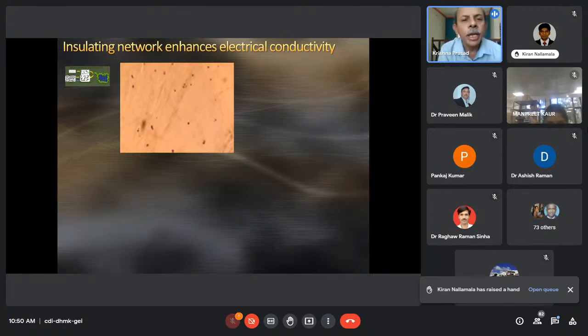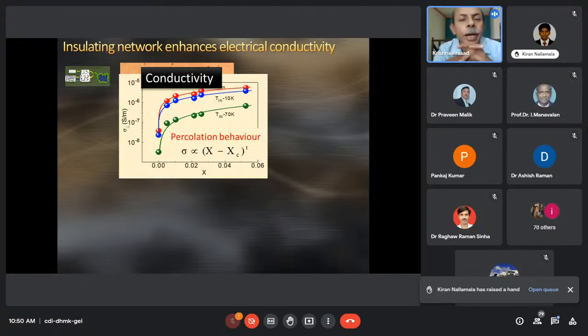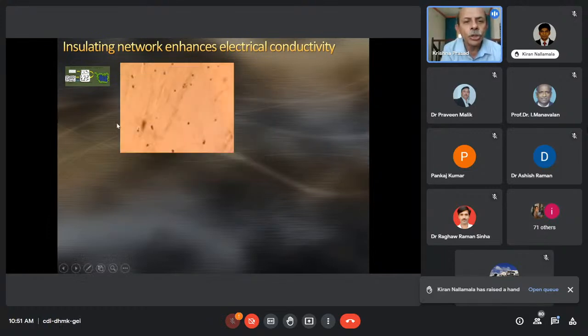And what you see here is the polarizing microscopy picture taken in the thixotropic network of the system. Lo and behold, to those especially from the liquid crystal background, this appears like any other ordinary nematic without giving you much hint about the porous network that is present because of the thixotropic system that the Aerosil have formed. Now, if you conduct electrical conductivity measurements by incorporating a conducting particle such as, for example, a gold nanoparticle into the system, drop a few gold nanoparticles into the system, what you see in the nematic, you have some dark regions which arise because of the presence of the gold nanoparticles.